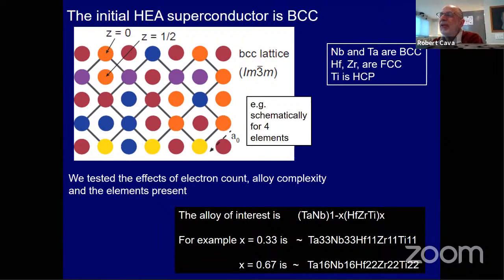Basically, the way to think about these high entropy alloys is you've stabilized a high entropy structure type with atoms in it that don't normally take that structure type. It's like a glass on a crystalline lattice. That's how I think of it. It's glassy in that there's a lot of different atoms mixed in there, but it's a crystal lattice in that it's a regular array of atoms.